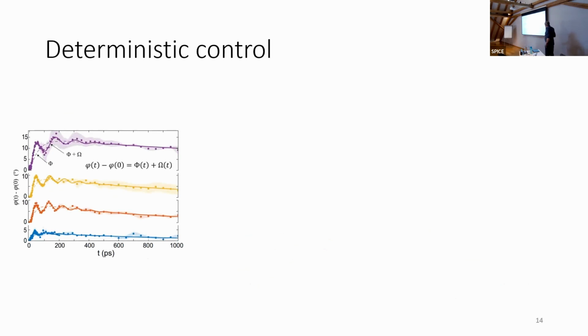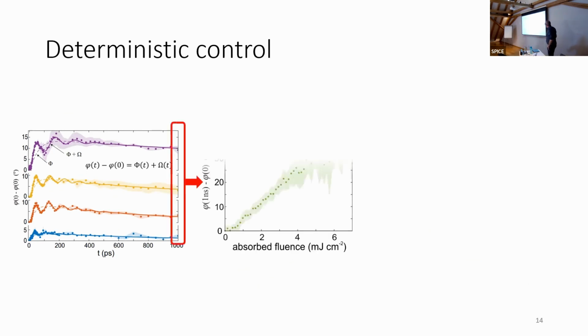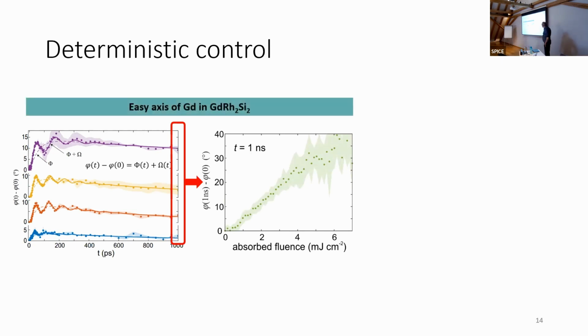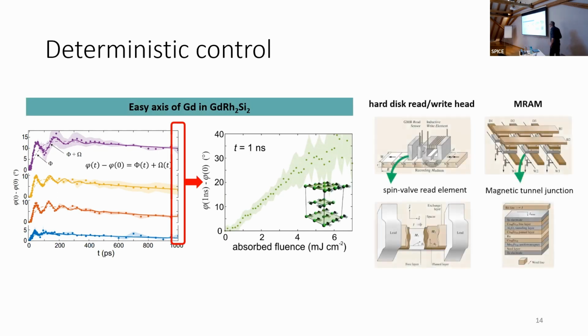So I'm going to briefly talk about what happens at very late delays when we don't have the displacive excitation anymore. So we also solved the spin structure for many fluences at one delay. This is shown here. This is again parametrized by that angle. And we see that we have a linear dependence. And so essentially, if we want to rotate the entire spin structure by a certain angle, we can choose a certain fluence. That is very deterministic and lovely for what some people would call switching or some version of control. You can imagine you can control something like MRAM with your laser pulse by rotating your entire spin structure deterministically.